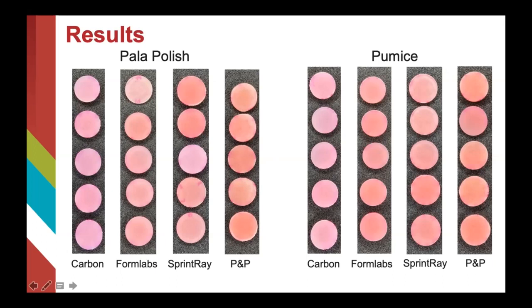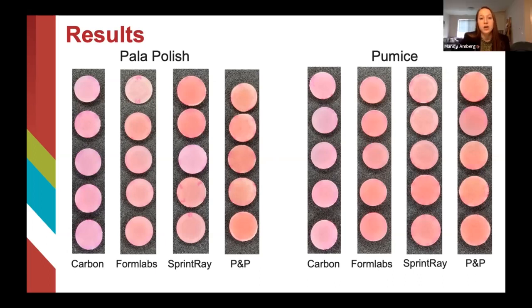So did you find variation when you test, for example, the gloss, or maybe you can test the roughness? Yeah, there were differences. We took 3 measurements for each and then took the average. There were differences in the values we found, but in a typical denture, you would find different surface roughness and different topography of the denture. So we thought that would correspond to the clinical scenario well, because different parts of a denture would be polished differently in real life. But on average, that's what we found.